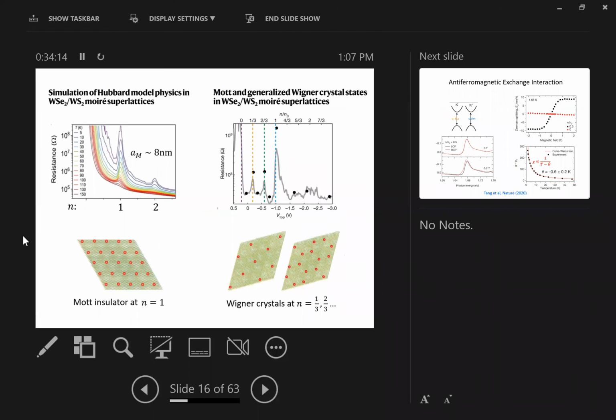And then in 2010, two experiments came from the Cornell group and the Berkeley group, that showed indeed when you have two doped charges per unit cell, there's a band insulator, there's a resistance peak. But when there's only one charge per unit cell, at half band filling, you also have a large resistance peak. So this is the Mott insulator. I'm going to call this n equal 1. n equal 1 means one charge per unit cell. It also means a half of a complete band filling, which is at n equal 2.